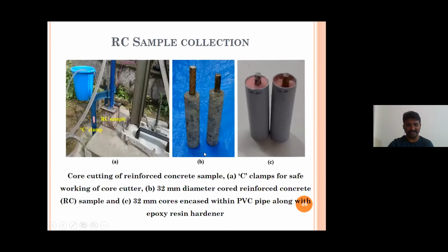So what do you mean by that? Remember, as I told you before, we had used an RC sample of 10 centimeter. This is the C clamp which we have used to hold this cube in between, and this is the core cutter. And I tried to get the perfect steel concrete sample of this kind. See here, this is the steel and this is the concrete. The rod is of 10 mm and the total diameter of this is 32 mm.